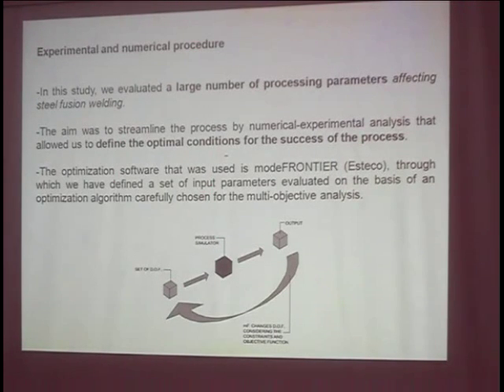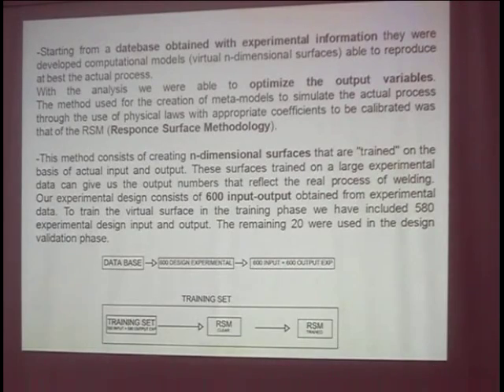The instrument we employed in these studies, modeFRONTIER, is a commercial tool which permits us to study a lot of processing conditions and gives us as output many mechanical and microstructural data, and in this way gives us the possibility to analyze a large number of experimental data, going to the optimization of the mechanical properties. The number of experimental data we analyzed is 600 experimental conditions in terms of different thicknesses, different heat input, different voltage and current during the welds, and actually 600 data in terms of tensile properties, fatigue and impact strength.